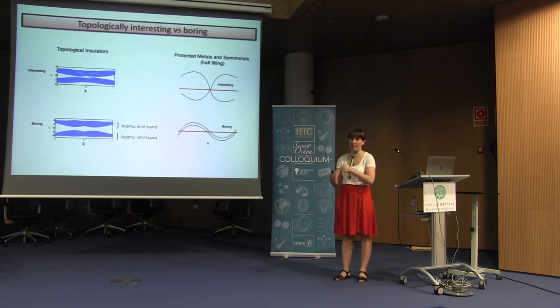I mean, the strong topology always connects the valence bands with the conduction band, and this is why it's interesting, because it always has to be in the middle of the gap, no matter what happens. You can have vacancies, or you can apply an electric field, and still, they will be in the middle of the gap. When you have corner states, if the crystal is ideal, they will be in the middle of the gap, but if some external perturbation happens, they can drift down to the valence band, for example.